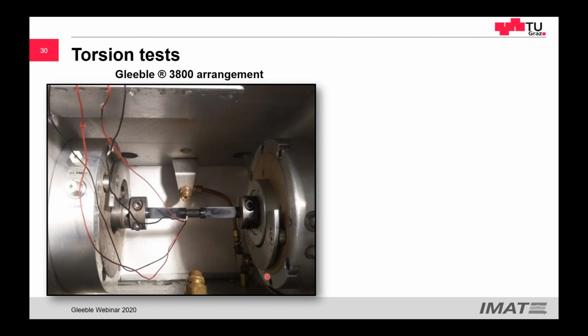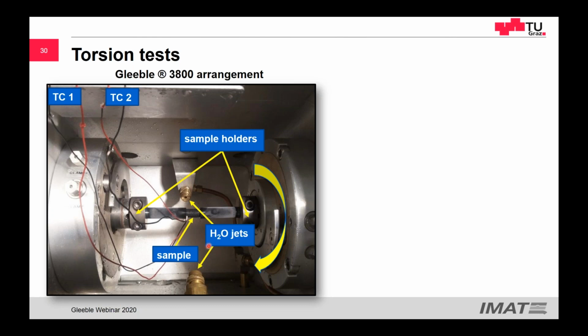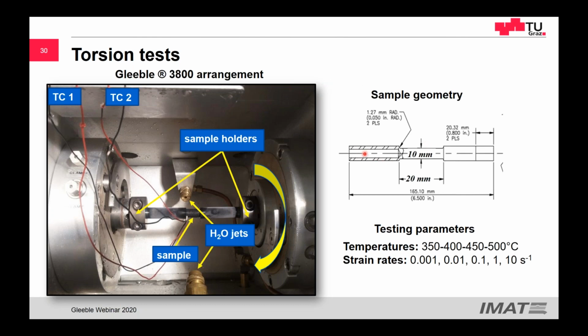So how to prove it? This is not that easy, and for this we use torsion tests. Again, very, very crucial and important compared to other works is to use the in situ quenching to stop any type of static recrystallization and modification of the microstructure. We have that one part rotates, we have the water jets, the sample is positioned here, so this is the type of sample that we used. And the sample is also hollowed in one part, like here. So the main idea here is that you get the same section in the middle of the sample as well as in the heads. So with this, you may reduce the gradient of temperature. And I said reduce because it's not gone completely. Still, the gradient of temperature is not that bad.